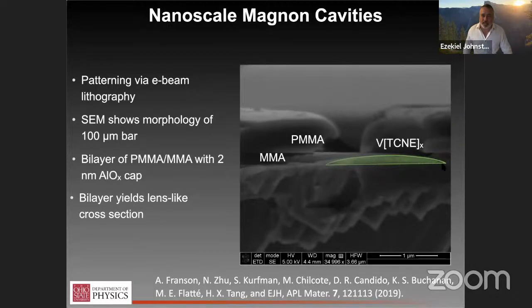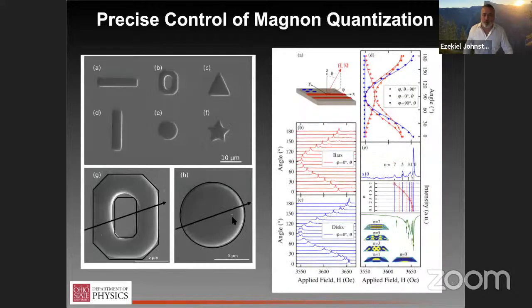And you can see in cross section, we get this sort of lens-like structure. This has to do with the fact that this is a CVD process. So people used to doing device fab are used to the low pressure regime where atoms come down directionally. Here we really have some gas flow dynamics that are giving rise to this shape. But the important point, and actually I realized I don't have this data on the slide. On the left-hand side, you can see we can make just about any pattern we want, just limited by the fidelity of e-beam, which is quite good.